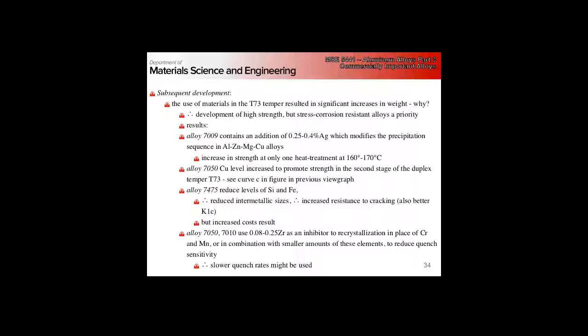The focus since that point has been the development of focusing on maintaining the strength but improving the corrosion resistance. This has been done by adding small amounts of silver, which modifies the precipitation sequence, or we can increase copper and rely on variations of the duplex heat treatment.